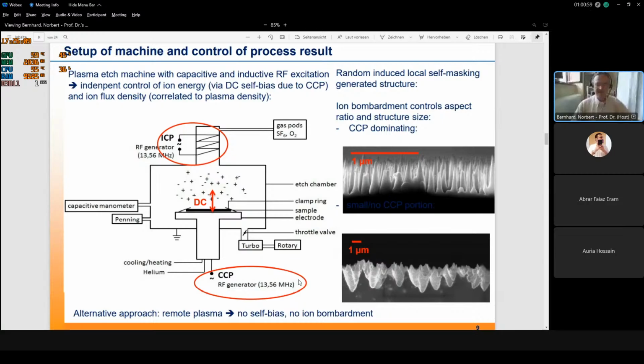And then we burn the plasma here, and just by the so-called self-bias of this high-frequency field, there is always a superimposed DC field created to the high-frequency field. And the DC field is such that the plasma itself is positive relative to the wafer. That means all the time we have a bombardment of the wafer surface by positively charged ions. I mean, the minuses here are just the electrons in the plasma. And by this bombardment in combination with the chemical etch attack by the fluorine, structures like this can be created.